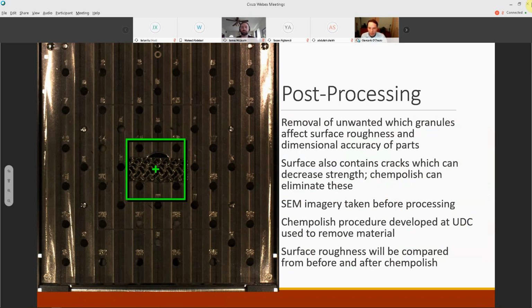All of these printed pieces have some unwanted steel granules that stick to them during the printing process, and these affect the surface roughness and dimensional accuracy of the parts to some degree. The surface may also contain cracks, which can decrease the strength of the part. So we used chem polishing to remove these. We took SEM imagery before doing any of the processing, then used a chem polish procedure developed at UDC to remove this unwanted material and cracks. Then we compared the surface roughness before and after the chem polish.